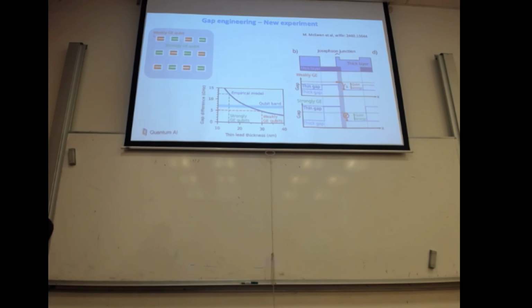And then they repeated exactly the experiment that they did the first time. They set up all of these in the one state, they measure very quickly to see what is going on, and to evaluate what happens when they have the striking of the gamma rays. And now let's see what happened. You see initially you have this statistic, right, that you might have some decay of this qubit. But then you see that when you have the gamma rays, the impact of this high energy, only the qubits that are weakly gap engineered get the decoherence. The others that are strongly gap engineered remain black. So they are not at all relaxed. And so this was great news, because we understand that with this gap engineering, we can correct this correlated error. So this was a very nice experiment.